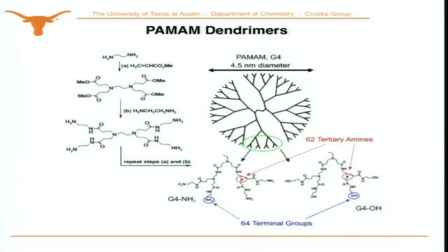Okay, so the first thing I need to tell you about, if you don't know already, is dendrimers. There's actually quite a bit of work in France, one of the real hotbeds of dendrimer activity. So you probably already know about these. But dendrimers are quite monodispersed polymers. They're not perfectly monodispersed, but they're as good as any polymer there is. They're prepared starting with an ethylene diamine core and then 2 reactions, a Michael addition reaction followed by an amidation reaction. And what happens during these 2 reactions is effectively the 2 primary amine groups here are multiplied by 2.